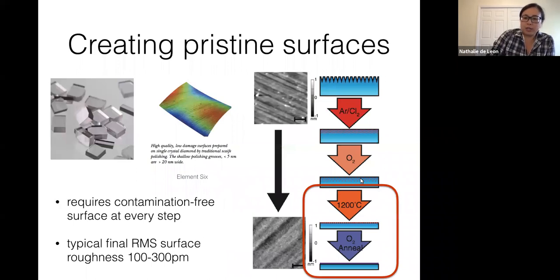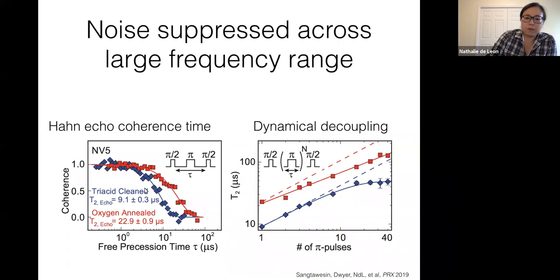So to try to understand and disentangle some of what's going on, we can zoom in on these last two steps and compare NV centers under this surface with NV centers under this surface. I'll refer to these as the triacid cleaned surface and the oxygen annealed surface. If we compare NV centers between these two last steps, we see that the Hahn-Echo coherence time gets extended by a factor of a few. This is on a log scale, so this is actually a big change.